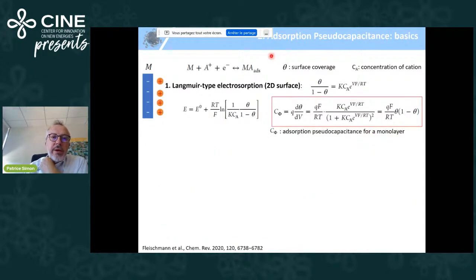Okay. Now, if we go back to the basics, Brian Conway reported what he called adsorption pseudocapacitance. When you adsorb cations onto a metal, you form adsorbed cations on the metal, and you can describe this adsorption by using a Langmuir-type electrosorption model, where theta is the surface coverage, which follows an Arrhenius law with voltage. Then you go back to a potential which depends on theta, the surface coverage, and you calculate an adsorption pseudocapacitance, because you have an electron transfer. For a monolayer it is given by QF divided by RT versus theta.